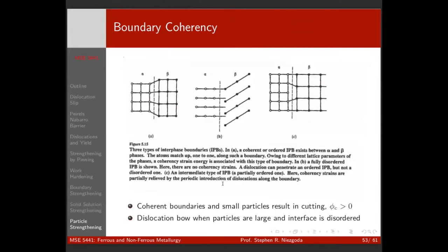We talked about boundary coherency before with interfaces. So in general, a coherent interface is going to be much easier to cut through than an incoherent interface, right? Because we have a nice path, we don't have to change our slip plane. When going through, our dislocations are going to come in and interact with other interfacial dislocations, and we might have a misorientation, and we're going to have to change directions, and we have dislocation reactions. So all that makes incoherent interfaces much more difficult to cut than coherent interfaces.